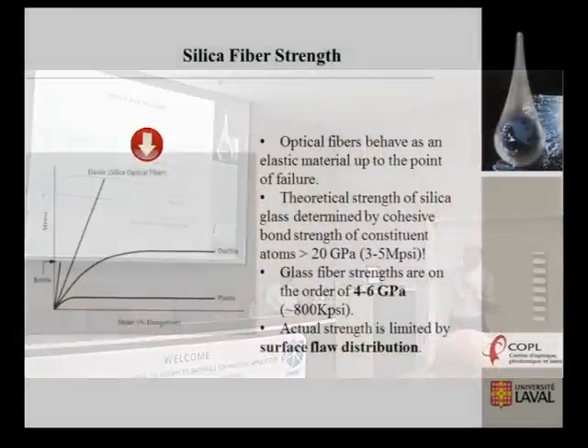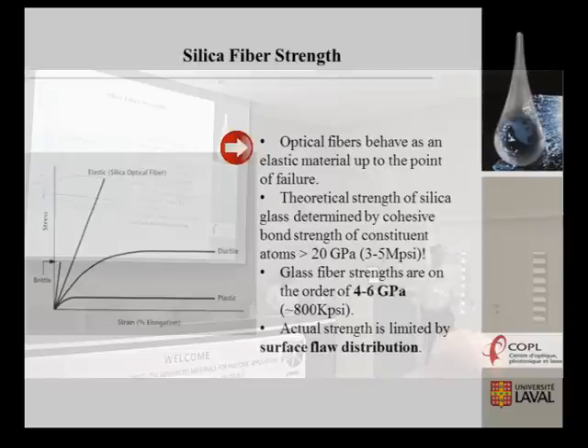And for that, the first thing, we draw the curve of stress against strain. This is the basic of the mechanical property of any materials, and the behavior of that, it can be elastic, ductile, or plastic. In the case of optical fiber, it's an elastic behavior, and this is dependent on the bond strength of the atoms of silica. This is something around 20 gigapascal, or something you say in the literature in mega-psi. And in general, for the glass fiber, the strength is around 4 to 6 gigapascal.